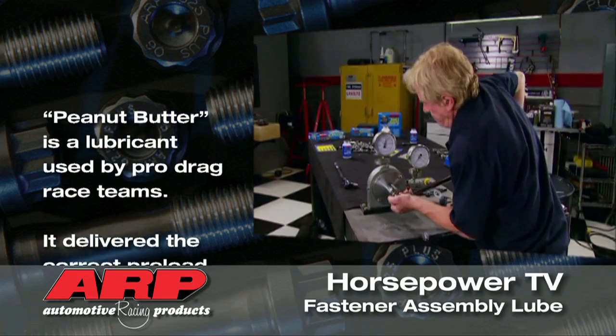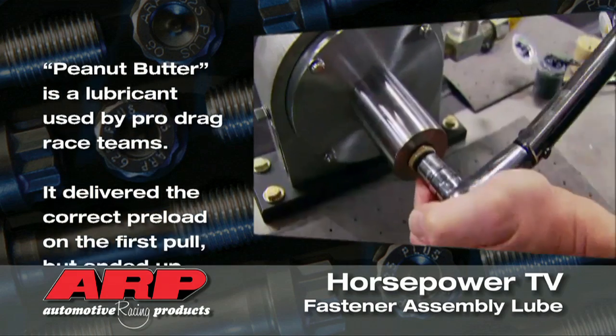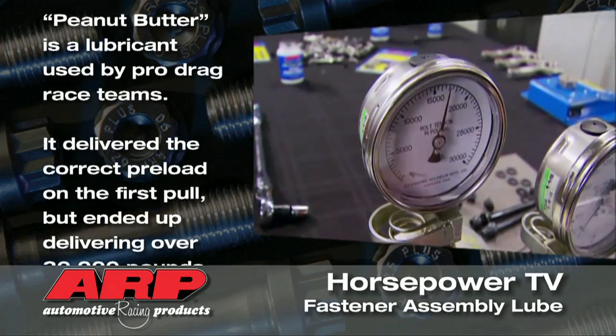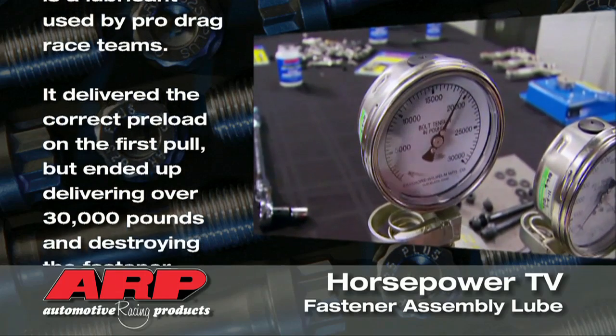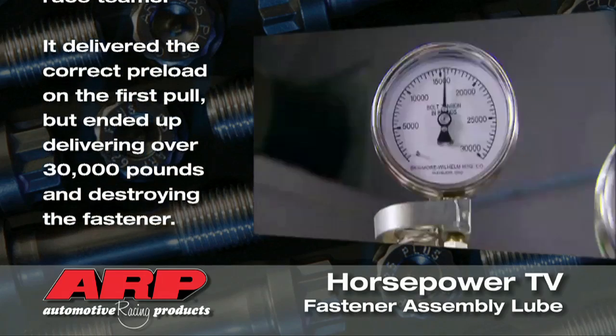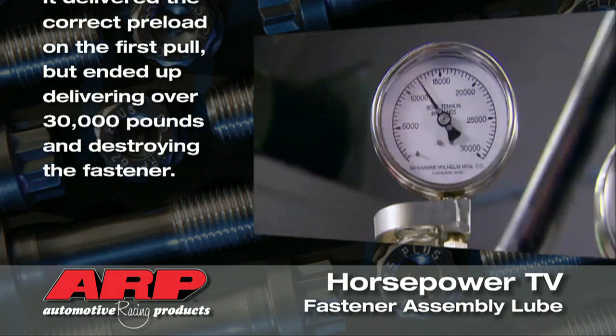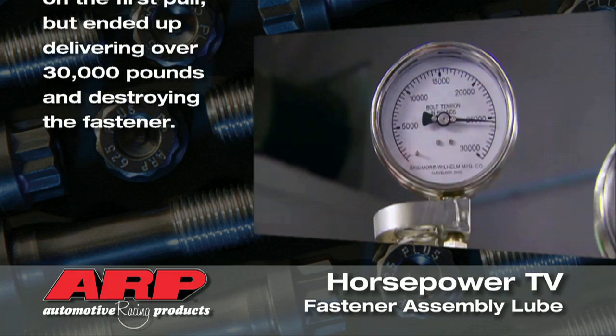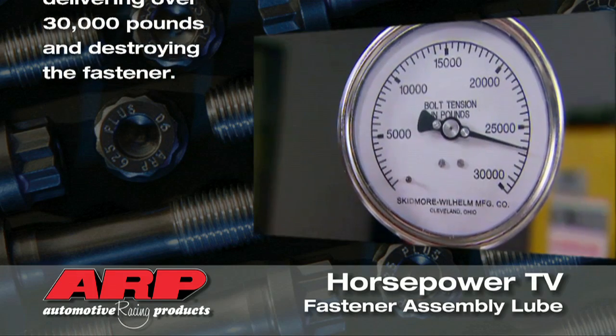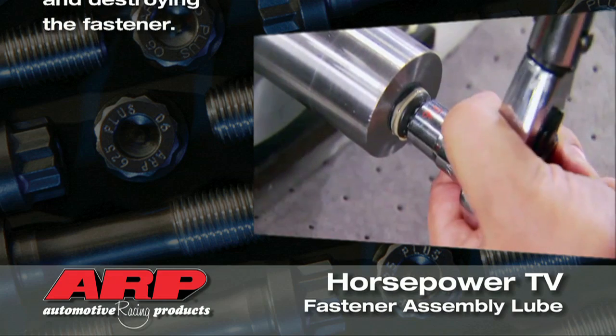I can see why they use it. It torques down at 18,000 pounds the first time. However, it's not recommended for street strip engines because on each follow-up cycle, the gauge goes up several thousand pounds above the target. On about the 7th cycle, we're all the way up to 30,000 pounds.